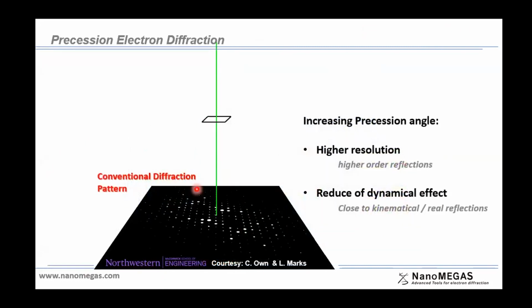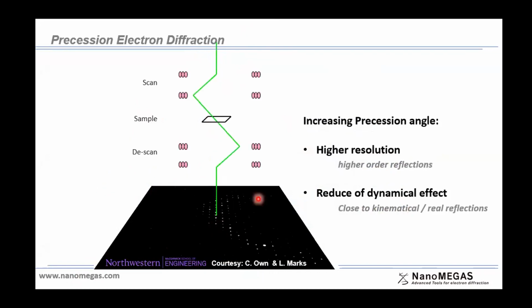Again, I have shown this earlier today, but for those that are not familiar with precession, instead of having a parallel beam passing through our sample and obtaining a diffraction pattern, what precession does is to tilt the beam before and after the sample. And the effect of this is actually a movement of the Ewald sphere. At the same time, we have quite fast rotation of this tilted beam around the optical axis. And what you obtain at the end is all these diffraction patterns together.